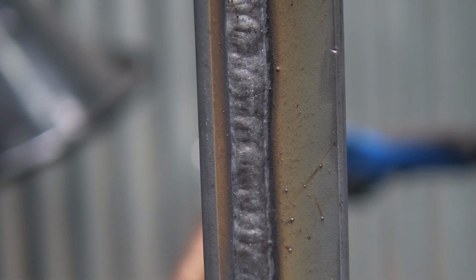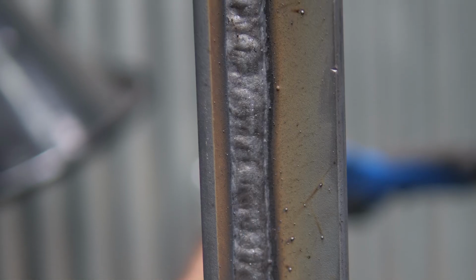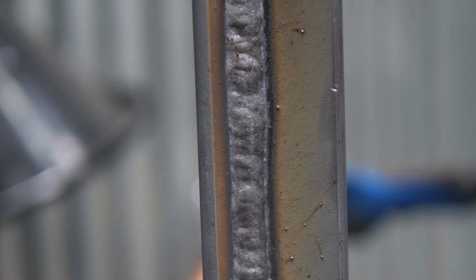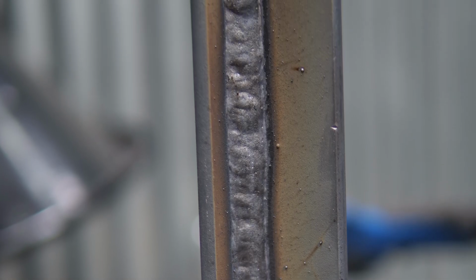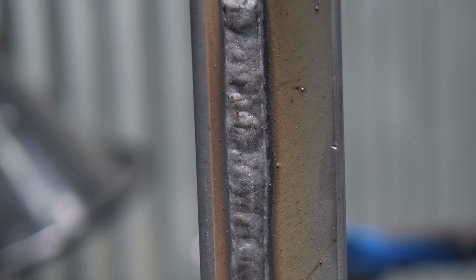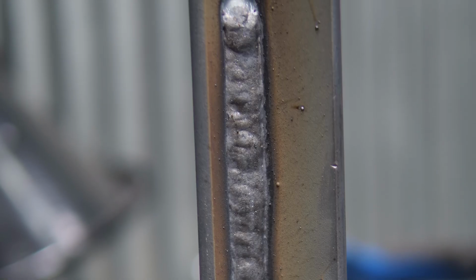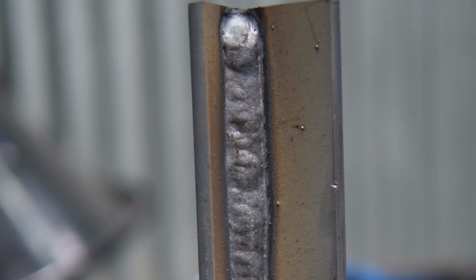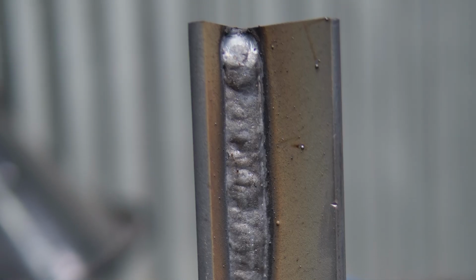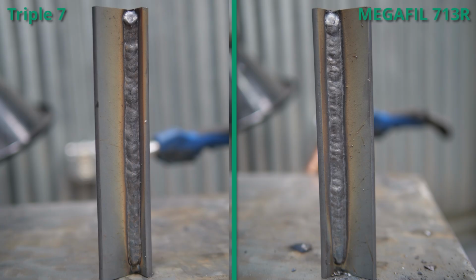Now I can see there is significantly more spatter with the MEGAFIL than there was with the 777. It's a lot more of a fine mist spatter all around the weld bead. Consistency of the weld bead, there's a little bit of inconsistency, but that's more my hand than anything. And then right at the top, there is a little pinhole that I didn't get with the 777. Now that also could be because I didn't pull the mill scale off of the plate, but just something interesting to note.